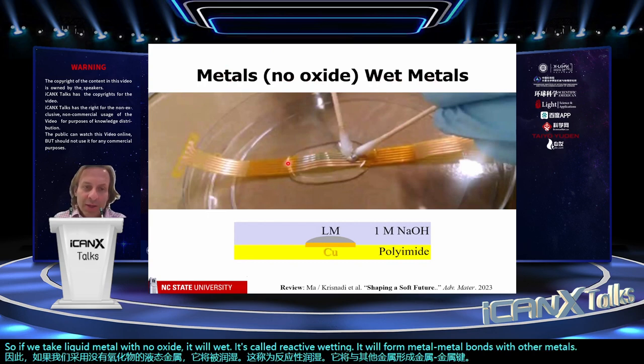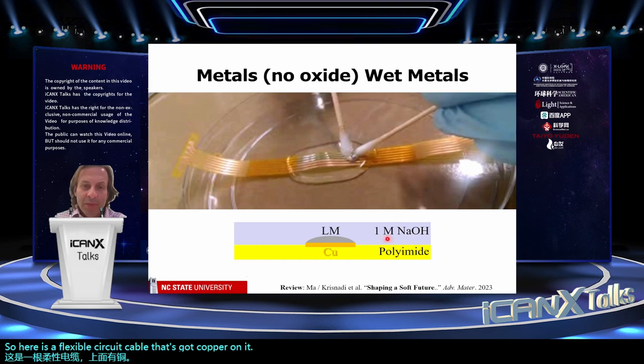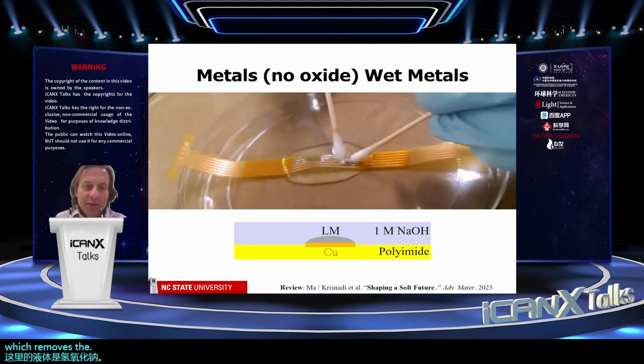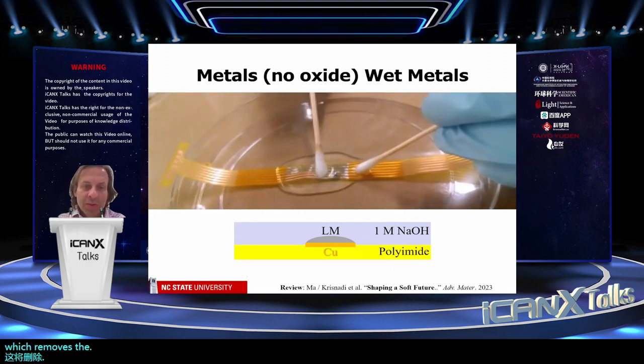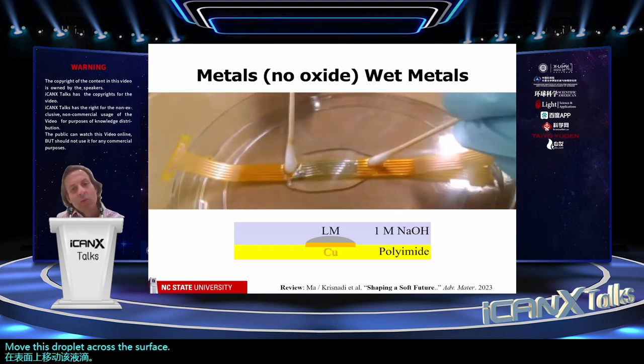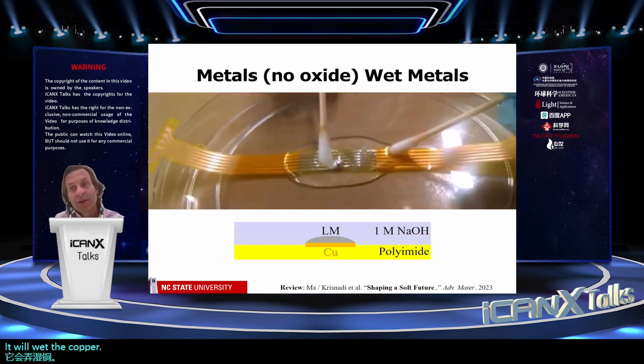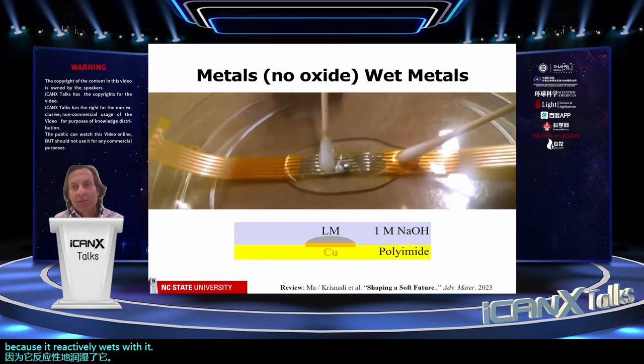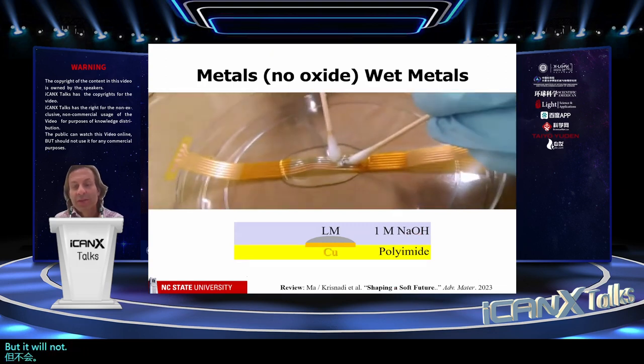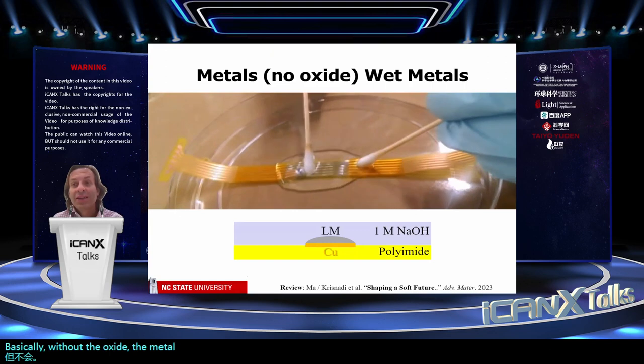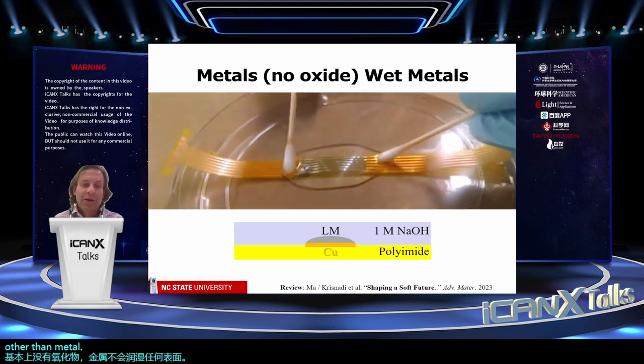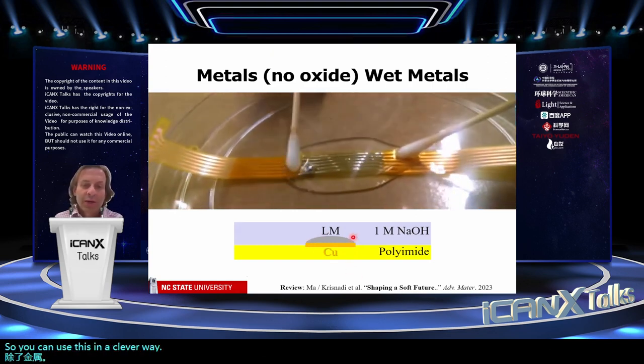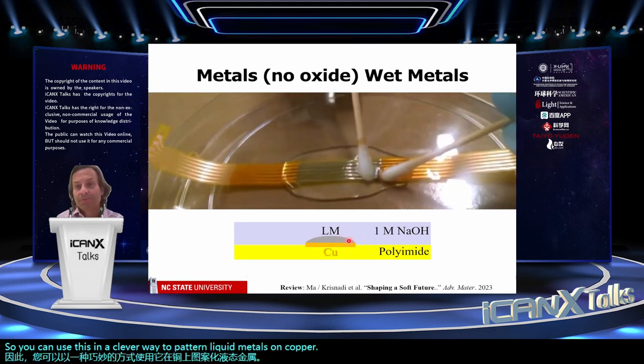So here is a flexible circuit cable that's got copper on it and polyimide, which is the polymer. And this liquid here is sodium hydroxide, which removes the oxide. So you see, as we just move this droplet across the surface, it will wet the copper because it reactively wets with it, but it will not wet the polymer. Basically, without the oxide, the metal doesn't wet any surface other than metals. So you can use this in a clever way to pattern liquid metals on copper.